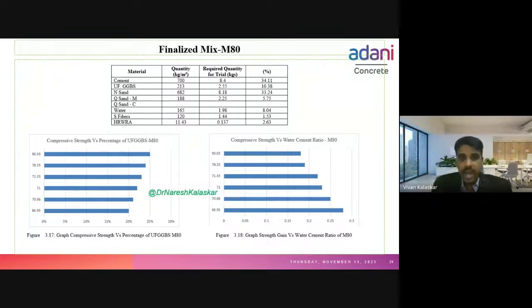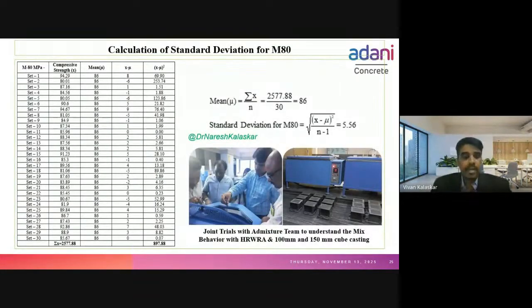So low water, higher good quality binder, and supplementary cementitious materials will be important. As you know, in Indian standard, we have a standard deviation up to M80 only. We have standard deviation for normal concrete only. For all higher grade concretes, the code has specified only 5 standard deviation. So in M80, we have also calculated the standard deviation for all these mixes. We have established the standard deviation is 5.56 for M80.